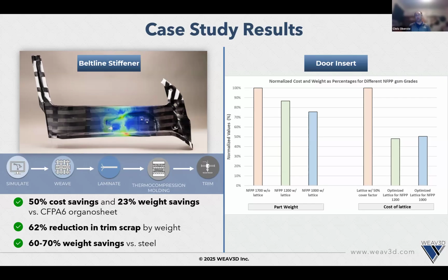With the thermoforming approach for some of these materials, what we actually find works best is if you either tack or fully laminate the lattice onto the sheet that you're starting from, and then you just co-form them together. For the case of the door insert, the non-woven mat comes unconsolidated. It's just kind of like a felt material. All you have to do is use a little bit of heat tack to attach the lattice to the surface in the right spot. Then you just stick the non-woven felt into a contact oven like you would normally, and it heats them both up together, melts them, and consolidates them into each other. Then you stick it into the press and it forms it into the final shape. So the natural fiber is just a needle punch mat, a combination of fiber and polypropylene. Exactly.